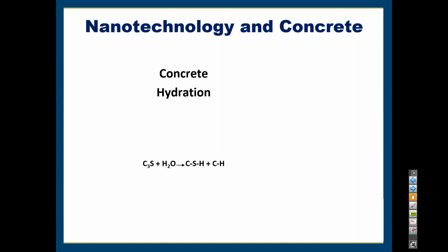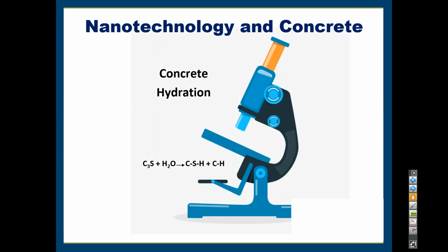So if we just look at tricalcium silicate and we add that to water, well, then that produces calcium silicate hydrate, which is the strongest part of our concrete. It's the stuff that holds everything together, and it's mostly responsible for the strength and the durability of our concrete. And then a byproduct called calcium hydroxide, the CH, which is not as beneficial to concrete. It participates in some of the durability mechanisms, some of the attack mechanisms that affect durability, rather. And so the less CH we have and the more CSH we have, typically would mean it's a better, higher quality concrete.